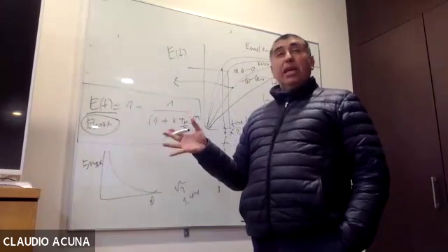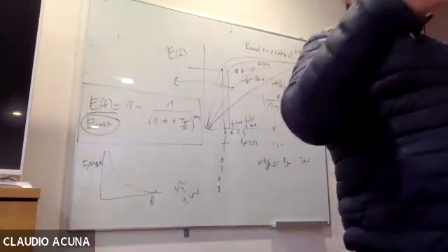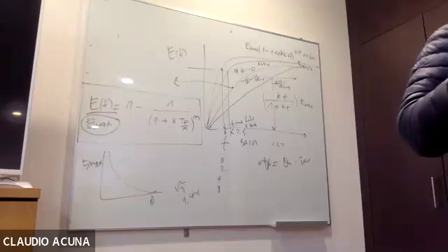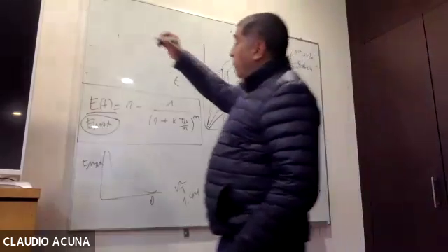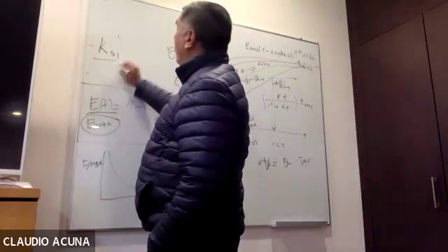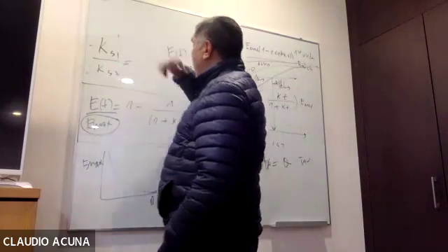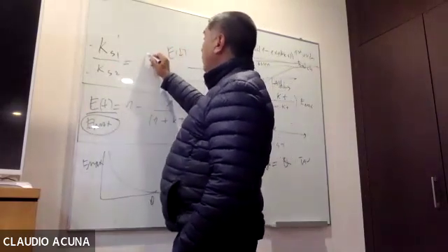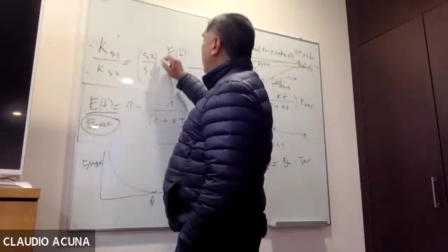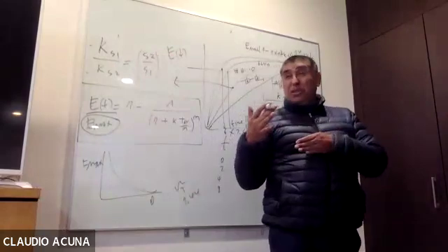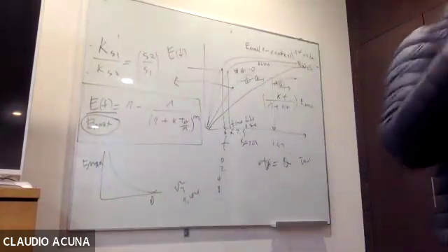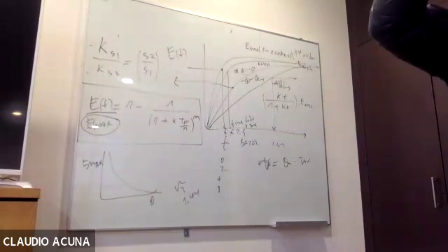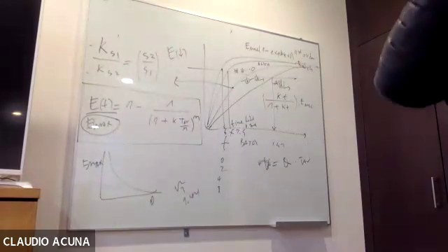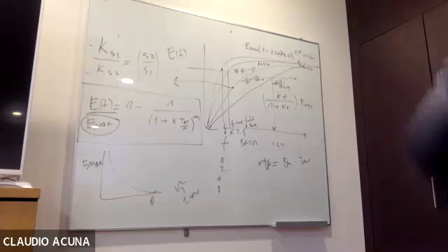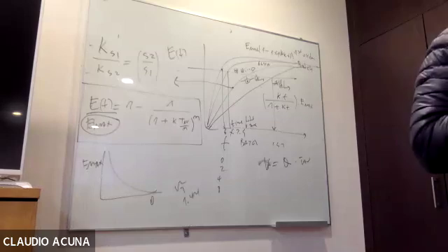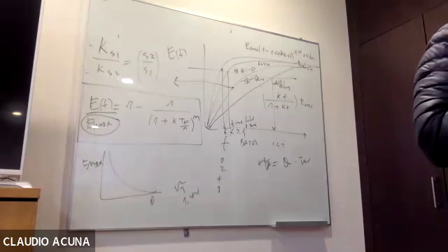K is a little bit tricky. If you are desperate and you have an experiment, let's say at 10 microns, and you want to see what happens at 100 microns, my recommendation will be K size 1 over K size 2 equals size 2 over size 1. Something like that. Because the interfacial area, at the end, will be volumetric fraction divided by diameter. So if you reduce the diameter, your kinetics will increase proportionally, 1 over the diameter. If you are desperate and you don't have a number, this is a good thing.